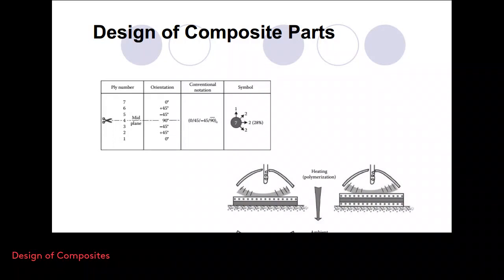mismatch of the thermal expansion coefficient between the layers, we see twisting or warping if there is no mid-plane symmetry. But in fact, if we have a symmetric structure, so we know that it is okay at high temperatures, but when the temperature decreases, certainly the structure will preserve its shape. So there will not be internal stresses, residual stresses, due to the mismatch of thermal expansion coefficient.